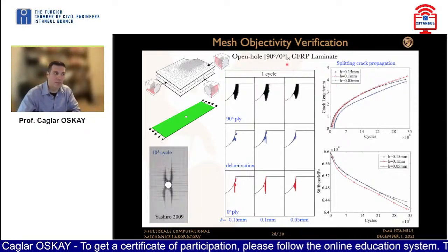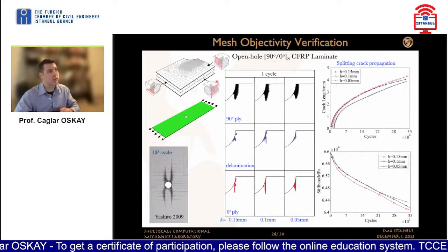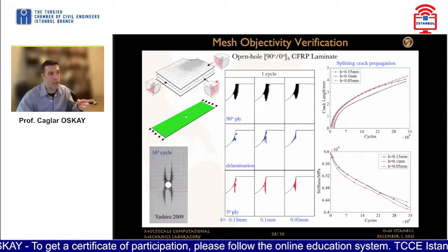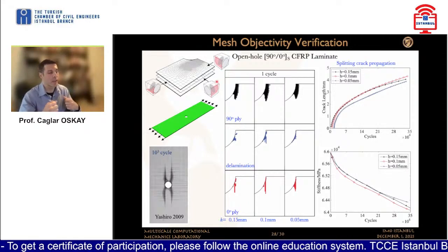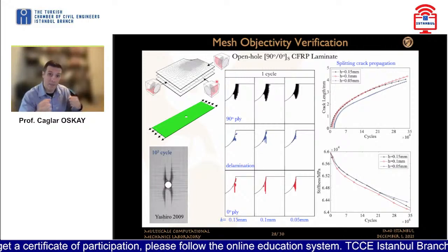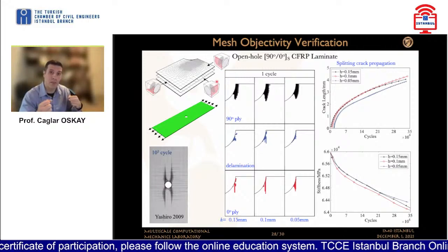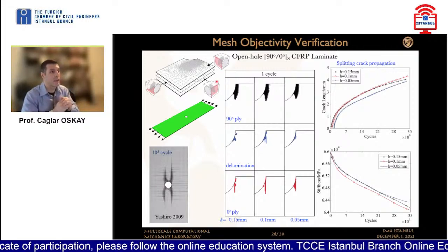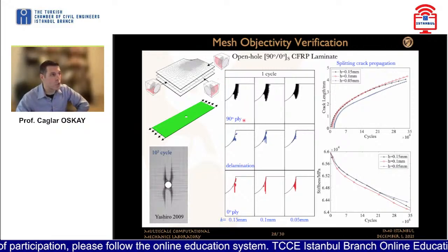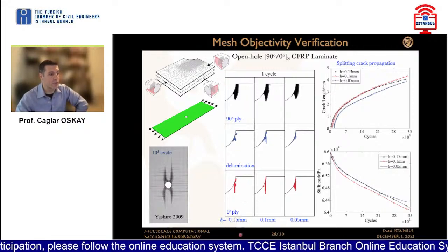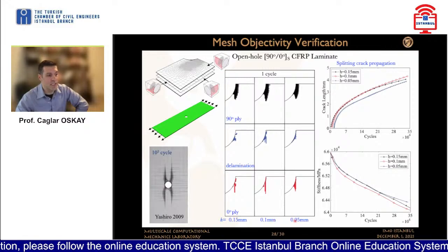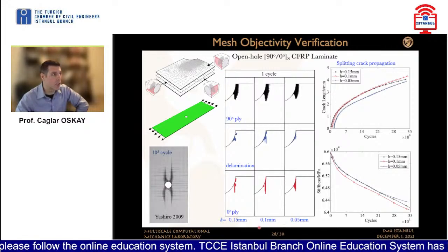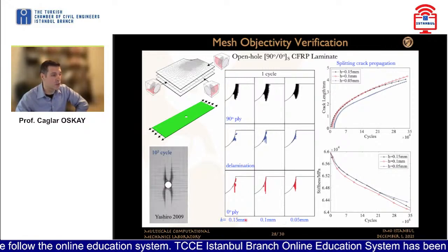Now we're looking at a fatigue problem. In this case, we're again looking at a cross-ply open hole CFRP laminate subjected to 95% of the ultimate strength fatigue loads. And we're looking at the evolution. So again, we have three different mesh densities that resolve the material and the structural scale.